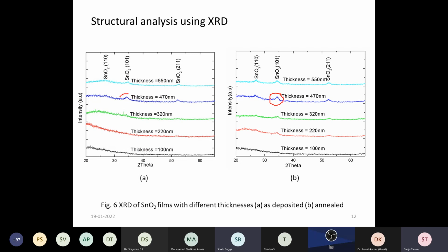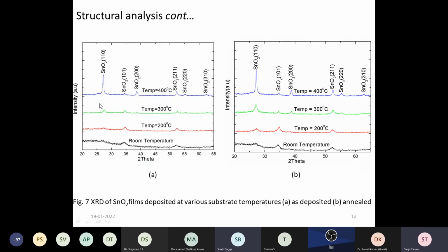We can calculate the grain size. Here we can see the peak is less broadened, and the same peak here is even less broadened, which indicates the grain size is increasing. For all the films, we annealed them for 2 hours at 400 degrees centigrade in ambient atmosphere. So as we anneal the film, the sharpness of the peaks increases for the different films. And in the second set, for the films deposited at different temperatures, we characterized them again. Here we can see that without annealing the peak is a bit smaller, while after annealing the peak becomes sharper. Why? Because when we anneal the film, the grains come close to each other and they merge, according to basic thin film phenomena. So the peaks become sharper after annealing at high temperature as compared to the normal.